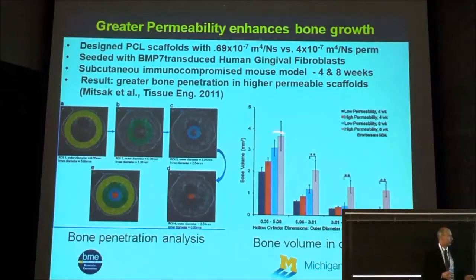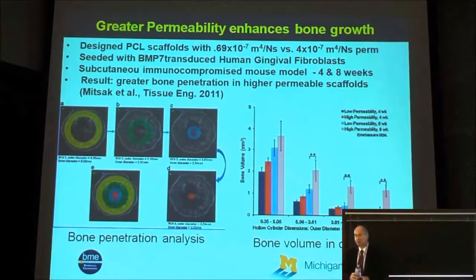And what you can see is that permeability definitely makes a huge difference in the amount of bone penetration, in that the highest permeability scaffold at 8 weeks, in the most interior parts of the scaffold, had much greater bone growth than the lower permeable scaffold. And that's intuitive: to get higher vascular invasion, higher permeable scaffolds lead to more bone growth.